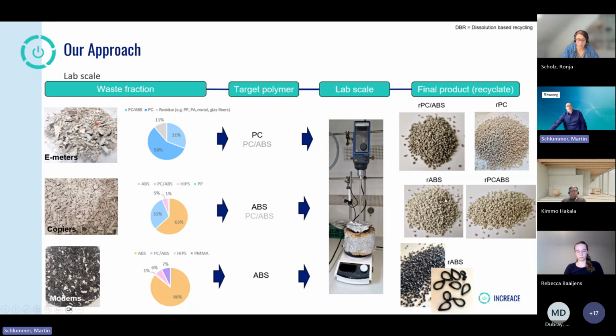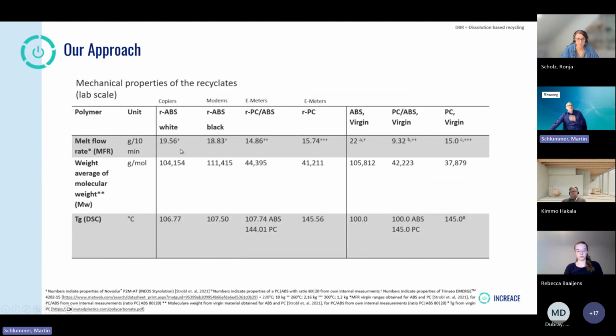The same is true here for the copiers. Here we also produced an ABS and a recycled PC ABS, and in the case of the modems we only looked into the ABSs. It looks like a quite simple process for sure. The purification steps are not pictured, so it is a bit more complicated than just one stirrer. But let's look into the results, and you see here that we end up with melt flow rates which are slightly higher than virgin, depending on what you take for virgin for sure.